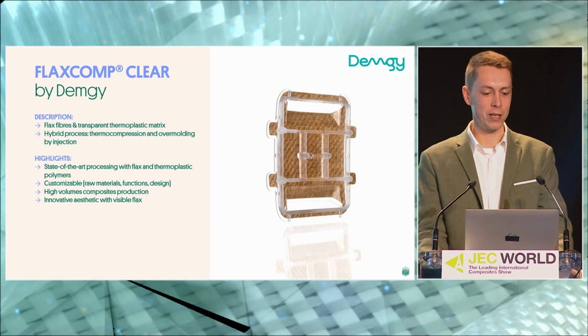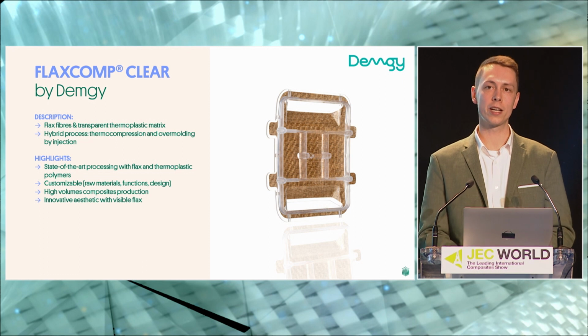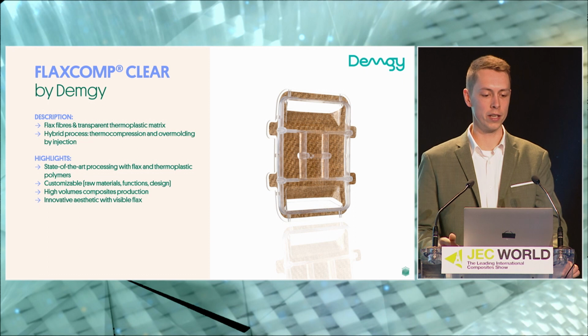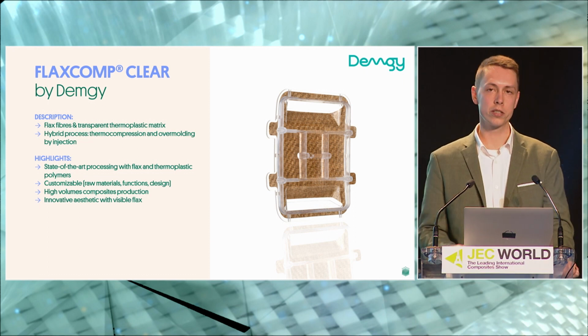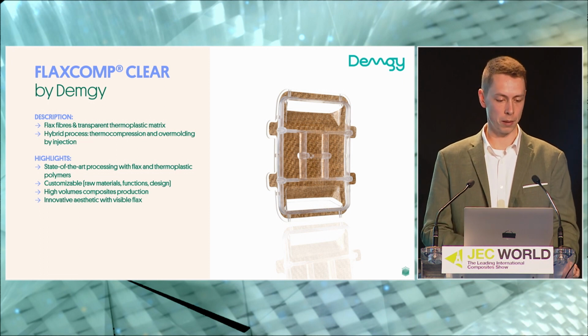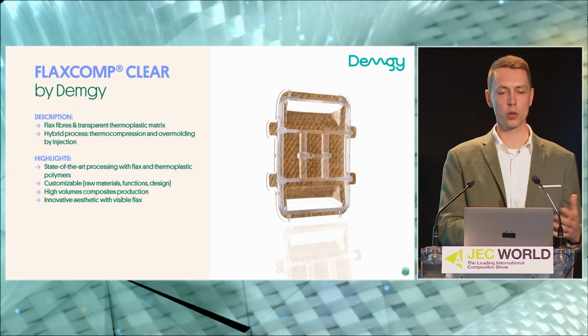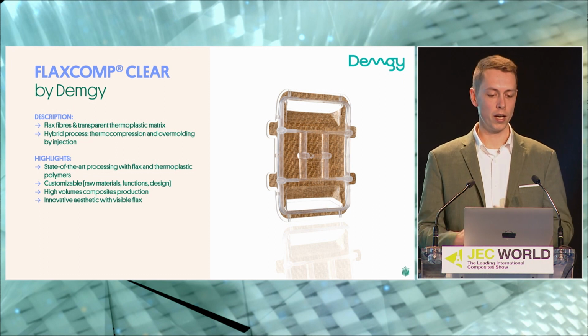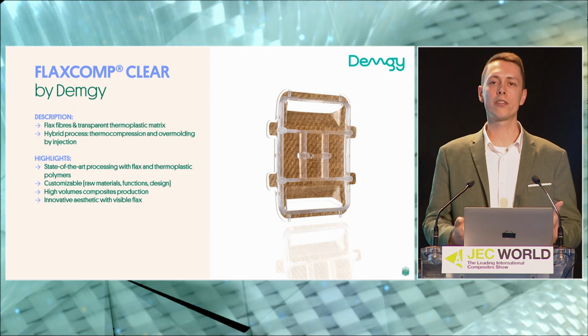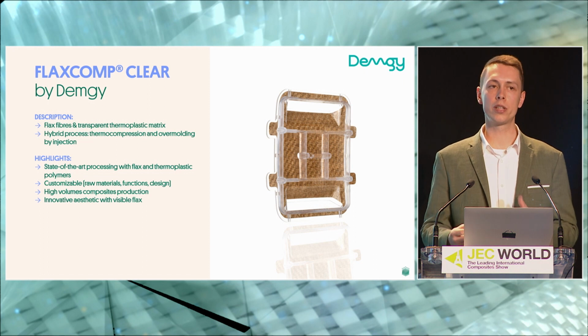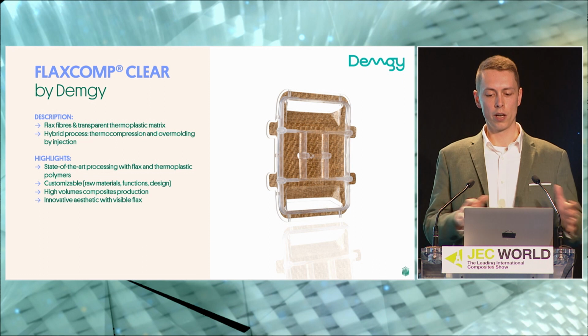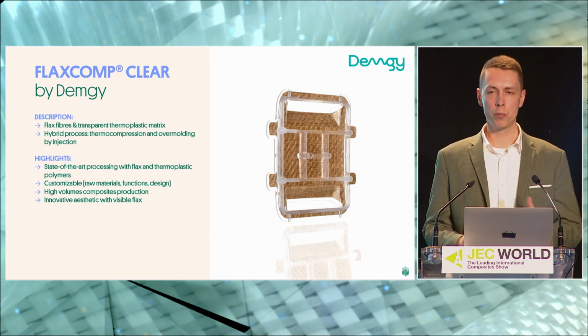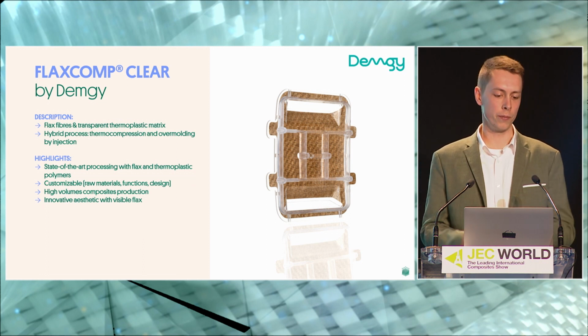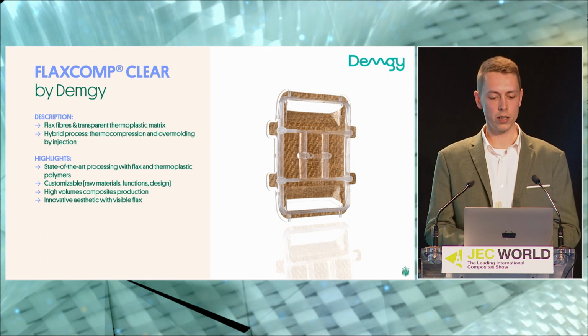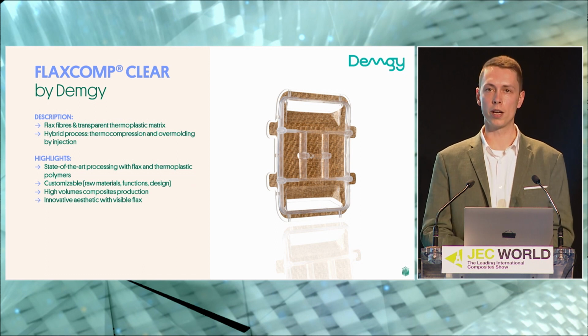So we will continue with some other nice examples. So this is from Demgy, one of our thermoplastic processing experts within the Alliance. And here they introduced their product Flaxcomp Clear, which is a combination of flax fibers and transparent thermoplastic matrix. So they're using a hybrid process, both thermocompression as well as overmolding by injection. And with this overmolding process, you can add functionalities to your product. So for example, you can make connection points to fit it with other parts or within your full structure, but also, for example, increase the local thickness of the part to, again, increase the local bending stiffness or bending properties. So Demgy can customize this material according to your needs, and it is also suitable for high volume composite production.